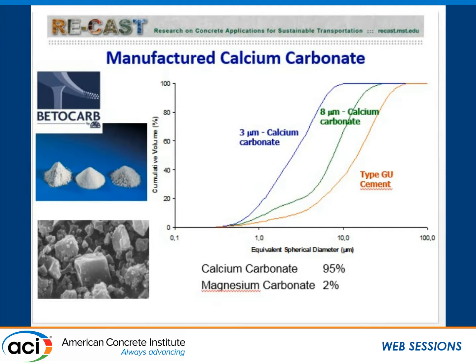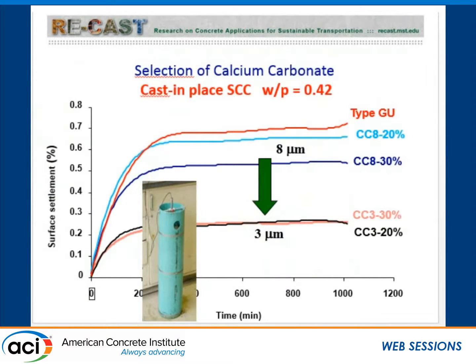So this is a logarithmic scale, and the D50 for this one would be 3 micron, and for Portland cement, it will be on the order of 15 to 17 micron. So this one is finer than cement, and this one is a lot finer than cement. And the calcium carbonate that was used over here is almost pure calcium carbonate, 95% very pure. And it was angular, because you mentioned also the morphology. It was angular and uniform in color. We're looking at different applications. I'll come to the applications.